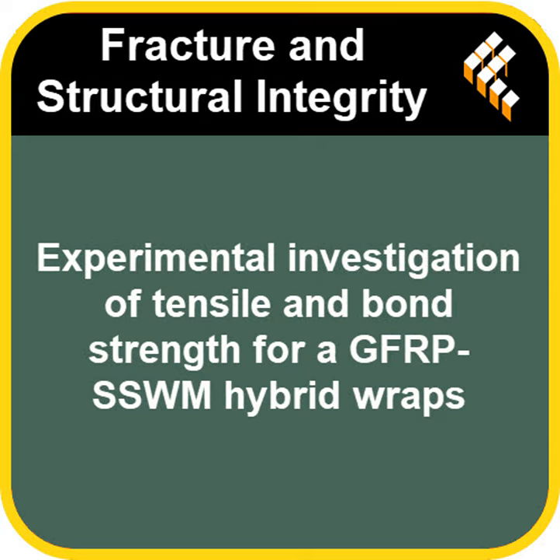So it seems like the hybrids are hitting a good balance, but what about the number of layers? They found something interesting there too, right? They did. A key recommendation was that 2-layer hybrids, like GS, might often be better than 3-layer ones, like GSG or SGS. Really? More isn't always better? Apparently not, for ductility anyway. Adding that 3rd layer could sometimes make the whole system a bit more brittle again. It reduced the overall ductility. Huh. So it's about optimization, finding the right balance, not just piling on material. Exactly. That 2-layer hybrid seemed to hit a sweet spot for balancing strength and that crucial deformability.